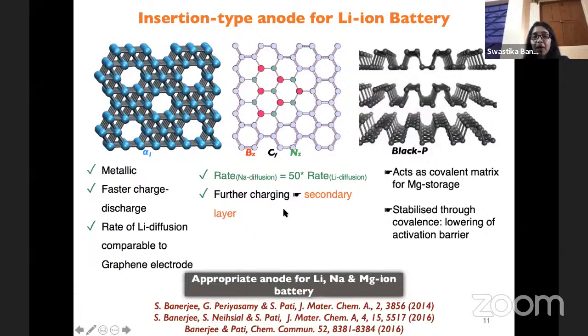When we look at the borocarbonitrides, we find that it is actually good in terms of diffusion for sodium, and it's even faster diffusion for sodium compared to lithium. And in the charging and discharging we studied, we find it can store a sufficient amount of sodium on this layered system. And we looked at the phosphorene kind of puckered structures, where we find that it acts as a covalent matrix and it stores the magnesium.